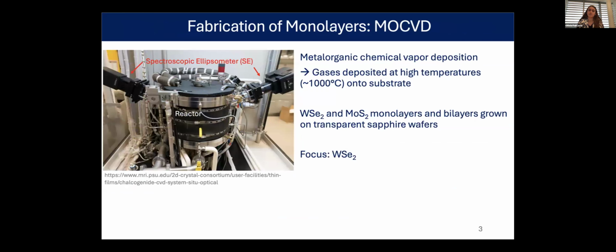So this growth, the metal organic chemical vapor deposition, happens in the MOCVD reactor, where gas is deposited at a very high temperature. Our growth temperature was 1,000 degrees Celsius onto a sapphire wafer, which serves as our substrate. So we were growing tungsten diselenide this summer. And the beauty of this project is we have the spectroscopic ellipsometer attached to the reactor chamber. So we can take in situ SE data,